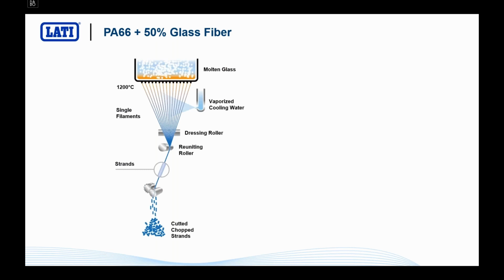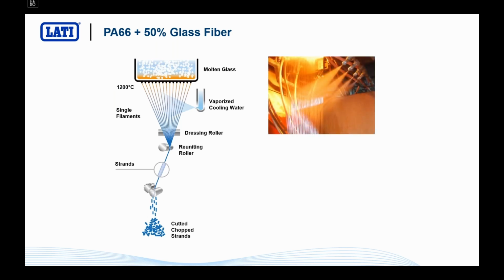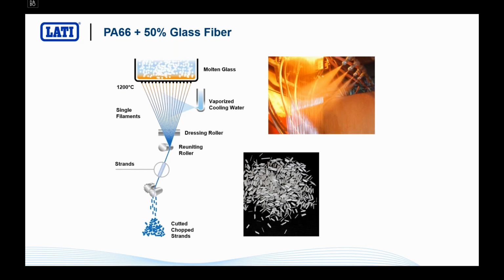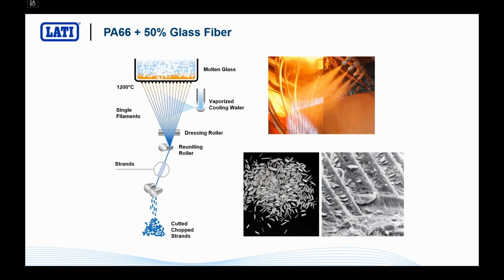Glass fibers are molten glass, which is spun into very, very thin fibers, which are chopped as chopped strands. These chopped strands are dispersed into the matrix, but it is not so easy to disperse them. And more than everything, they will provide a very bad looking surface on ordinary injection molding general purpose polyamide-66 50% glass. Let's see what is the difference in the surface finish, so in the aesthetic of your part, by using an ordinary general purpose polyamide-66 50% glass and another formula which has been tuned from a matrix point of view in order to boost, to increase, to improve the quality of the surface finish.